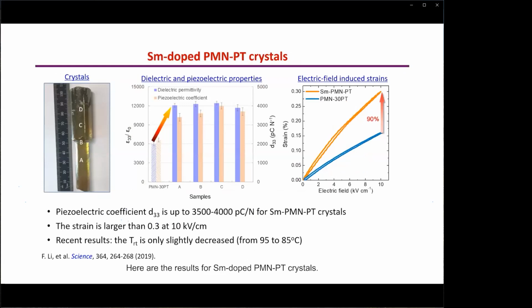Here are the results for samarium-doped PMN-PT crystals. As expected, the dielectric permittivity and the piezoelectric coefficient are really high. The piezoelectric coefficient d33 is up to 4,000 pC/N, and at a field of 10 kV/cm, the strain is larger than 0.3%. This is really good for low-field actuator applications.